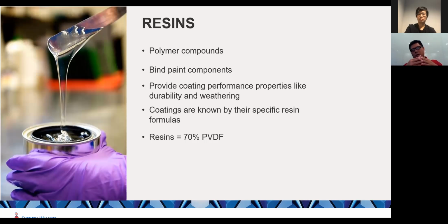That means within the entire formulation of the coating, there's maybe about 50% of that which is resin. So 70% of that 50% is PVDF. And the remaining 30% is acrylic. Okay.